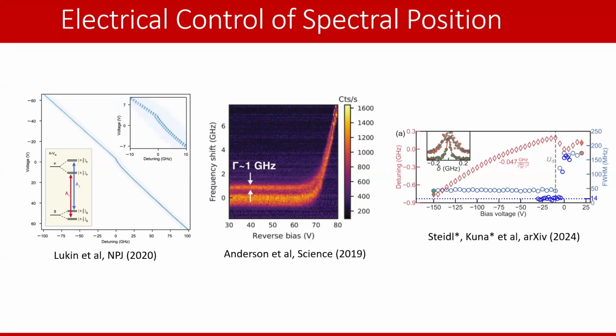So this actually does make the diode look a little weird. If you look at this work, it's a Schottky contact on epitaxially grown, nice, lightly n-doped silicon carbide on a substrate that is more heavily doped. That more heavily doped region has an ohmic contact on the bottom, so they get a nice IV curve. But if you imagine the contacts that I've made, you'll get some diodes pointed at each other. And so it has this terrible looking IV characteristic. But that's okay, again, because you only need the depletion region part.